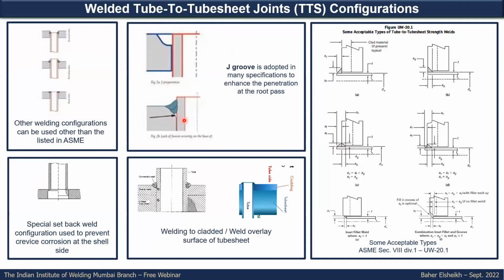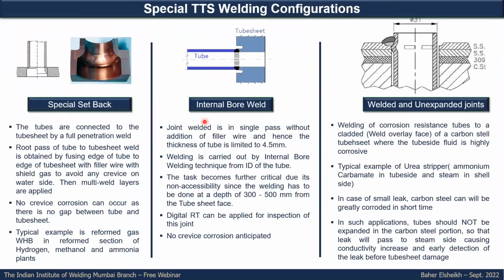And there are known limitations for the inspection of this weld joint, especially at the root pass. So in this case, it is highly advised, and in some specifications of some well-known companies in the industry, they recommend using only the J groove because of this reason. In some other applications, you might apply the tube-to-tube sheet joint to a cladded or weld overlay face of the tube sheet. And in some other cases, it is highly advised not to do expansion, like what we can see here, only welding, and we will see later why this recommendation is advised.